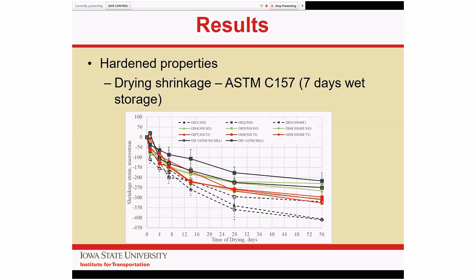And the higher the compressive stress in the steel, the higher the tensile stress in the concrete, and so the higher the risk of cracking. And you can see pretty clearly here that the three systems containing silica fume, the black dotted lines, had relatively high shrinkage. All of the others did quite a lot better. A couple of them did crack out. But the best ones, again, seem to be the ones with the shrinkage reducing admixtures.